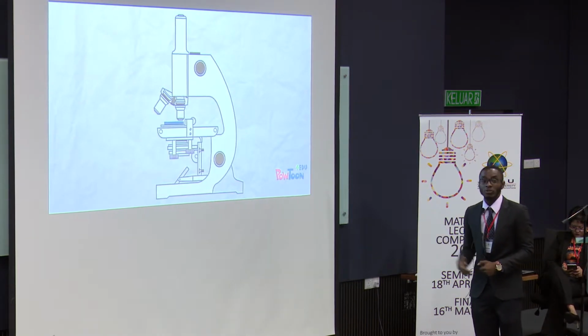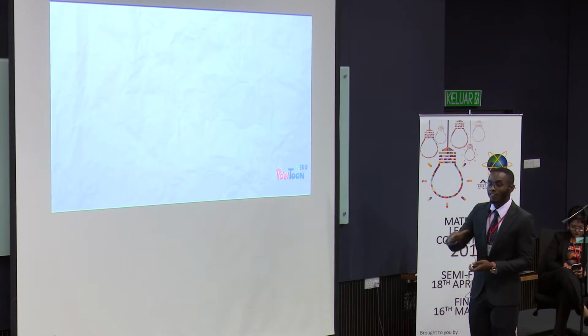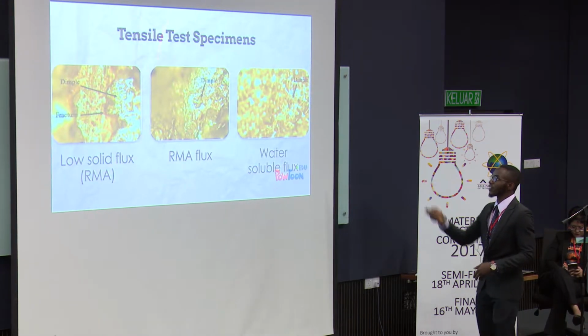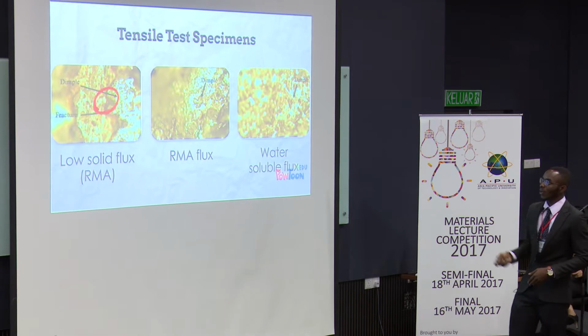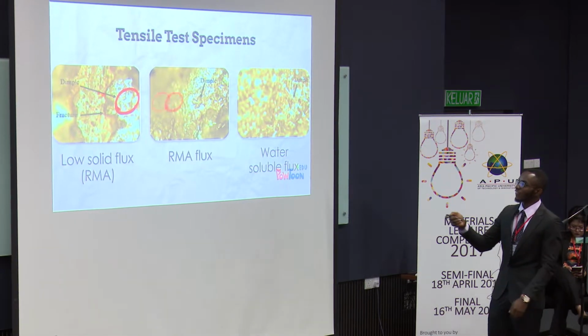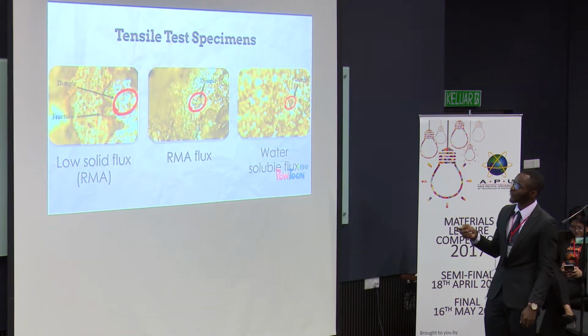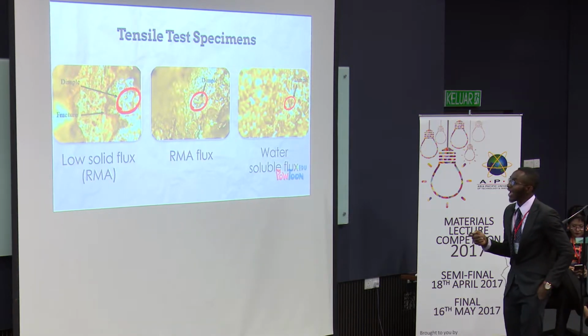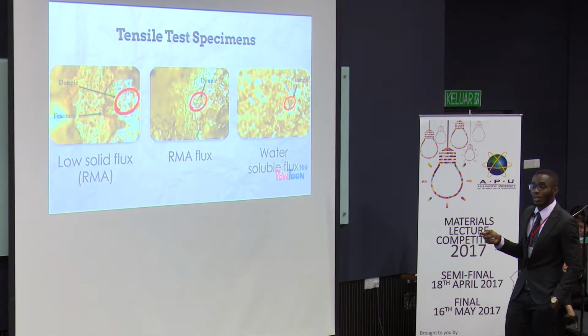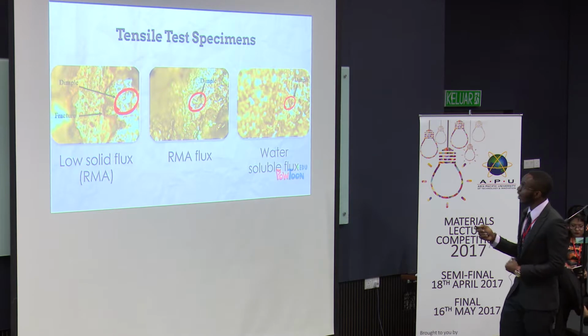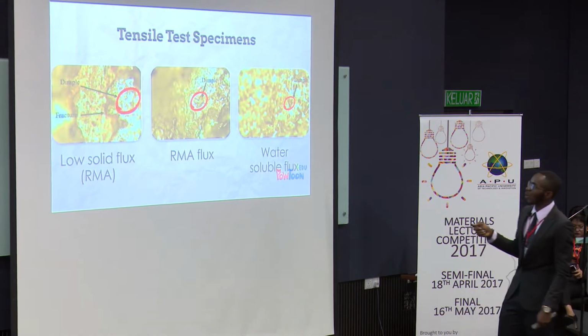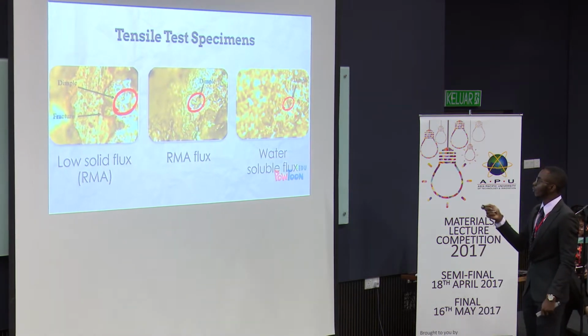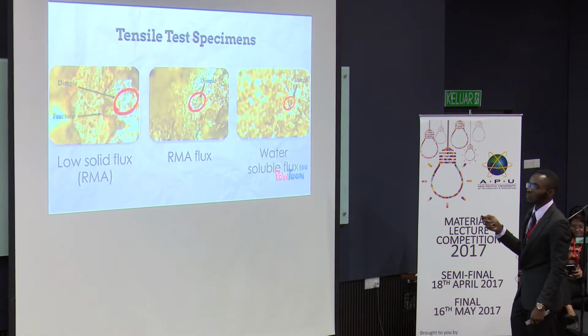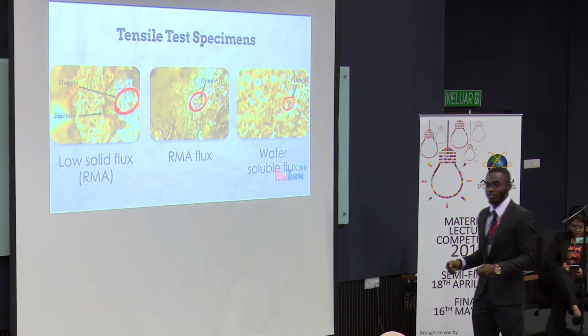Now, using an optical microscope, we can then see the surface of each specimen. Now, let's observe the surface of the tensile test specimen. We can see, for the low solid flux, as I mentioned earlier, we have a huge fracture on its surface. And we also have a dimple, which is quite huge on its surface as well. For the RMA flux, we have a slightly smaller dimple. And for the water-soluble flux, we have the smallest dimple with no fractures on its surface.